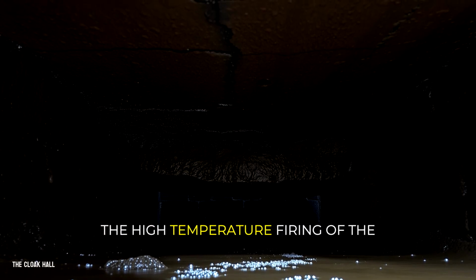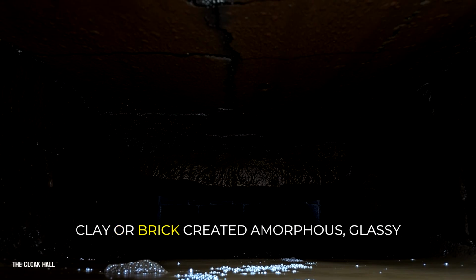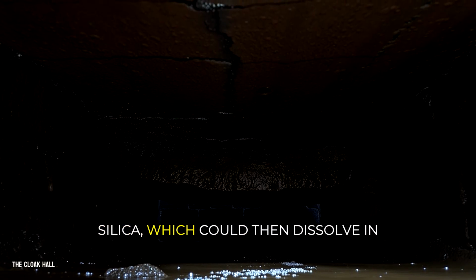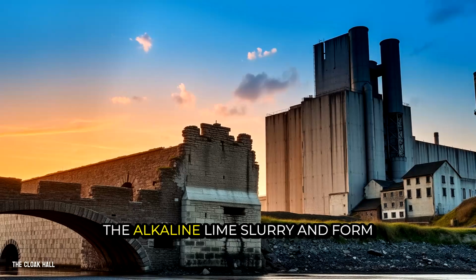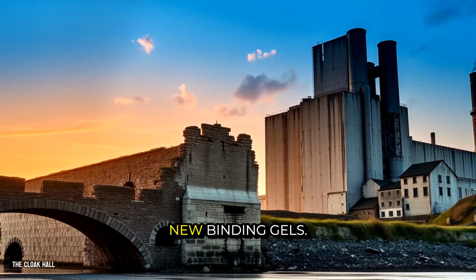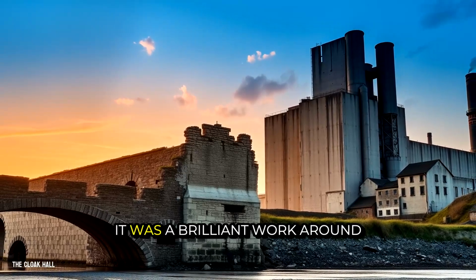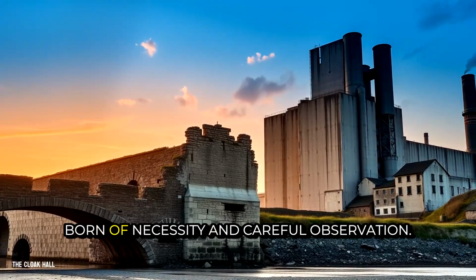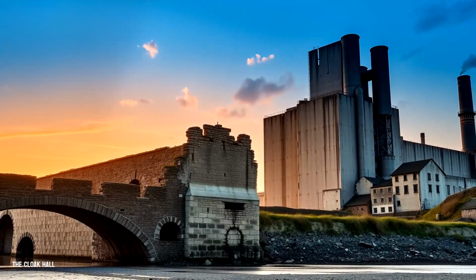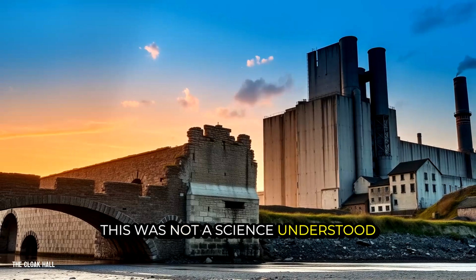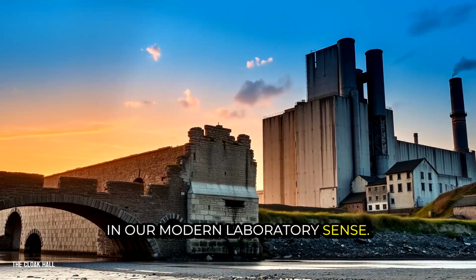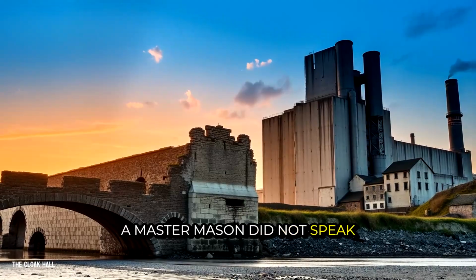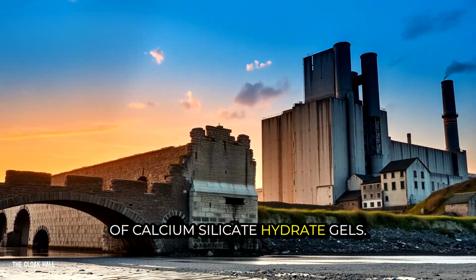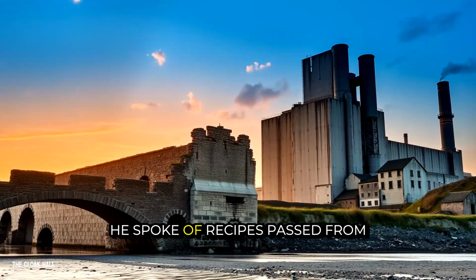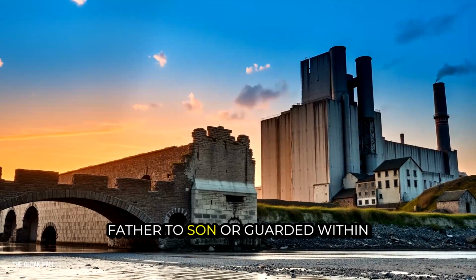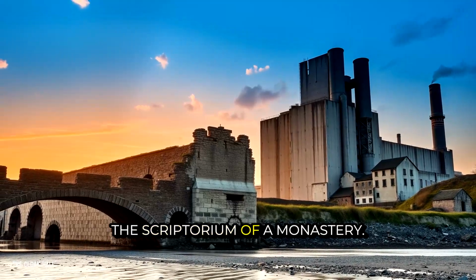The high-temperature firing of the clay or brick created amorphous, glassy silica, which could then dissolve in the alkaline lime slurry and form new binding gels. It was a brilliant workaround born of necessity and careful observation. This was not a science understood in our modern, laboratory sense. A master mason did not speak of calcium-silicate-hydrate gels. He spoke of recipes passed from father to son, or guarded within the scriptorium of a monastery.